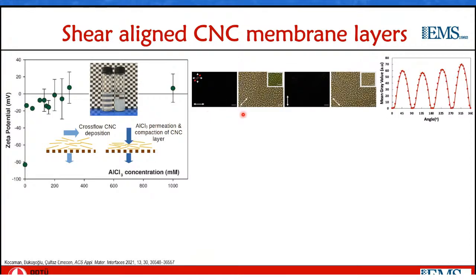And this is now our membrane on the more porous, less transparent support, but we still wanted to see how the alignment on the membrane, on the porous support, was. So here again, you see the flow direction, and we really nicely see that as a function of the angle between the flow direction and the polarizer, we see an increasing and decreasing light intensity, with maxima occurring at 45 degrees and so on, showing that there's alignment in the flow direction on the membranes after the aluminum chloride permeation and compaction treatment to stabilize the layer on the support.